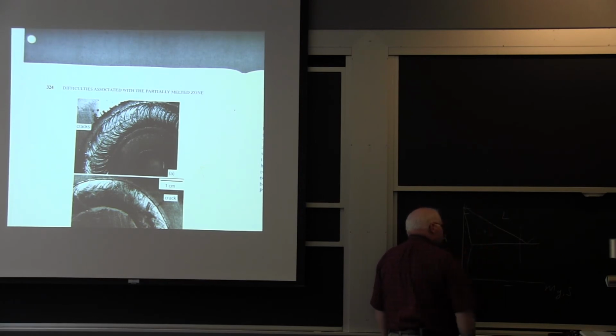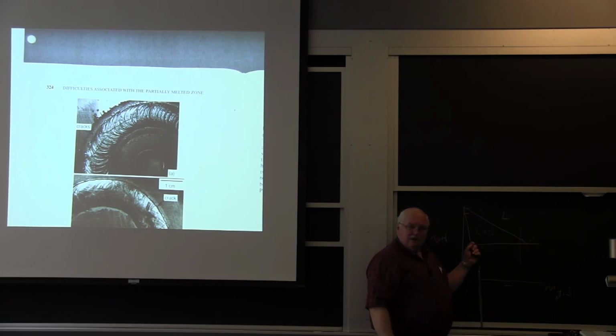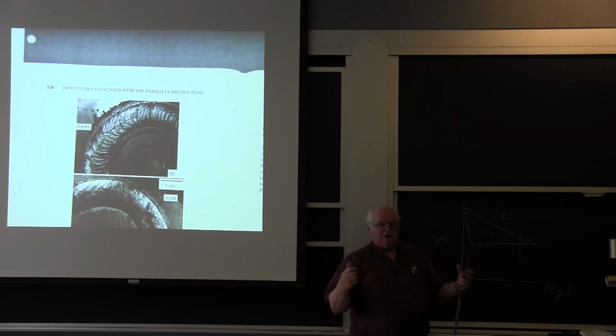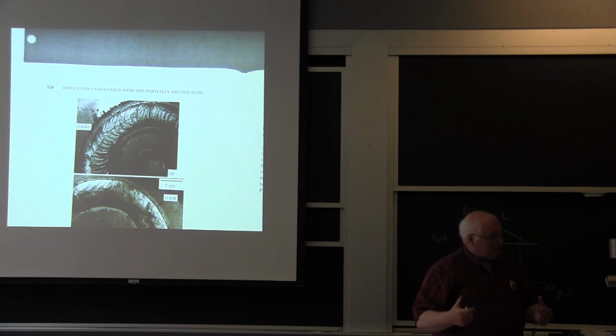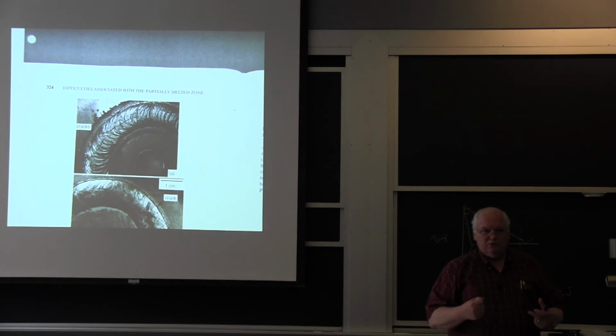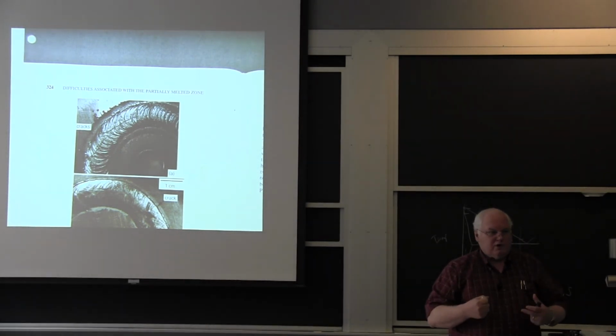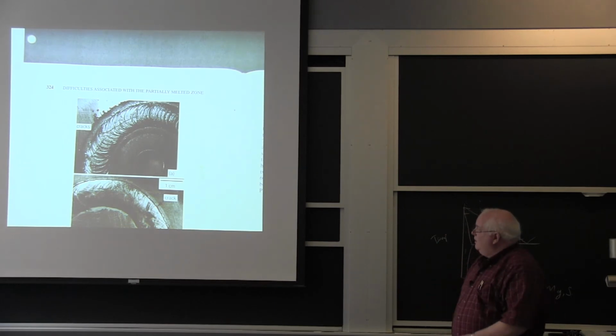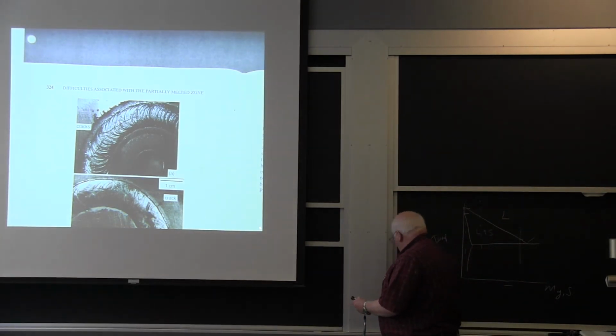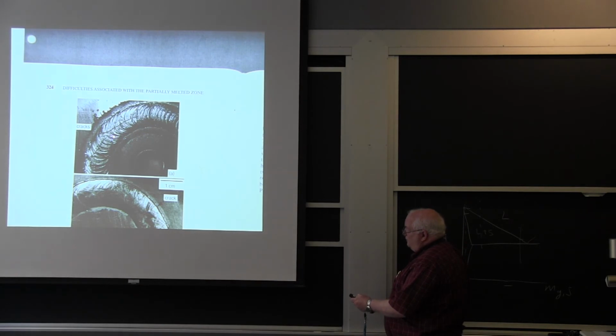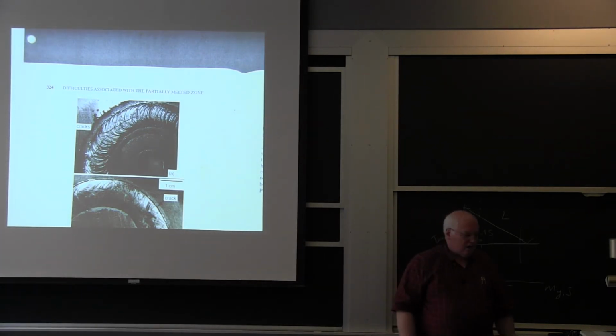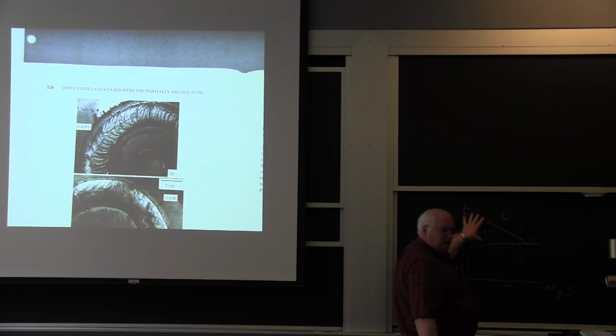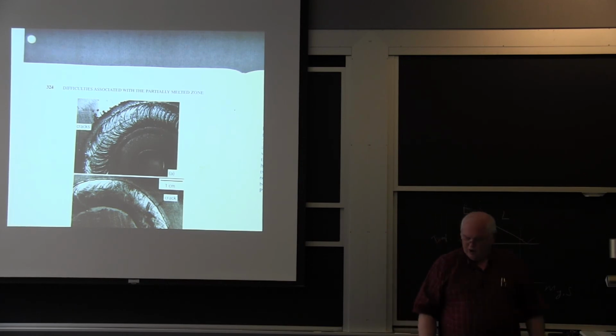If you end up mixing a weld metal and a base metal that one's highly alloyed and the other one's lightly alloyed, you'll have a very wide freezing range. Very wide freezing range means more delta T when you're in this liquid solid region. More delta T in that liquid solid region means more total strain. More total strain means more potential to crack. Okay? So it turns out if you take 6061 and weld it with 1100 aluminum, you're liable to end up with a crack because you've got a wide freezing range. Same problem with the nickel copper alloys. Okay? Just liquation, what we call liquation cracking.